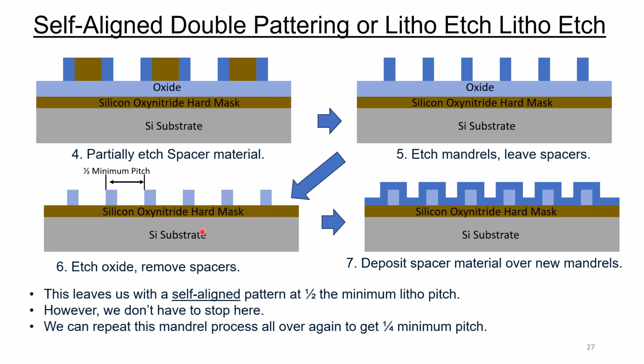But we don't have to stop there. Now we come in with another set of spacers, and we deposit spacers around the oxide. We're using the oxide as a new set of mandrels. So once again, we deposit a spacer around the oxide. Now we move to the next.